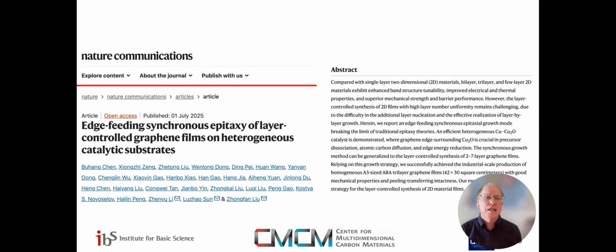And then in another paper, this time from the Beijing Graphene Institute, they came up with a method to grow up to 7-layer, apparently single crystal graphene. Now, I think for both of these papers, the obvious thing that needs to be done from my perspective is we need to make macro scale mechanical measurements on the N-layer samples, because there is the question, have they properly stitched together or not?